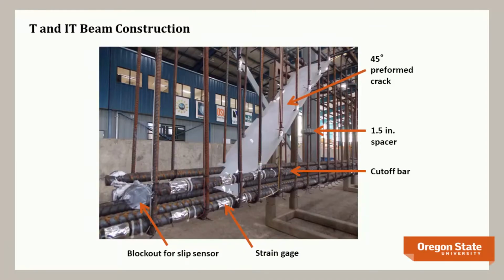We make this really hard on the girders, right? To simulate those diagonal cracks, we cast inside the girder, when we make these things, a polycarbonate sheet, right? So we take away all that aggregate interlock, or what people believe is aggregate interlock as a shear transfer mechanism, and we make either our stirrups and the flexural steel crank up high demand in those because of that.